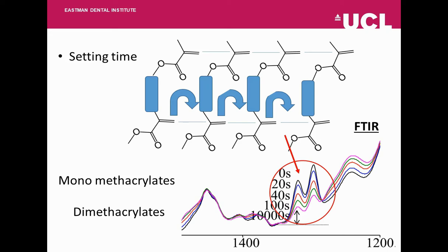Upon activating the polymerization of a monomethacrylate, such as PMMA, there is a rapid reaction, and like the animation just shown, the formation of a long polymer chain. However, often when you use a monomethacrylate, you have some unreacted monomers within the chain, which cause leakage, which is a problem with the commercial PMMA, later leading to toxicity. These problems arise in the commercial products. However, our composite consists of dimethacrylates, where after 50% monomer conversion, there is a second reaction, like we've shown in the animation, and the chains cross-link. So 50% conversion is required to ensure no free, potentially cytotoxic monomer can be released.